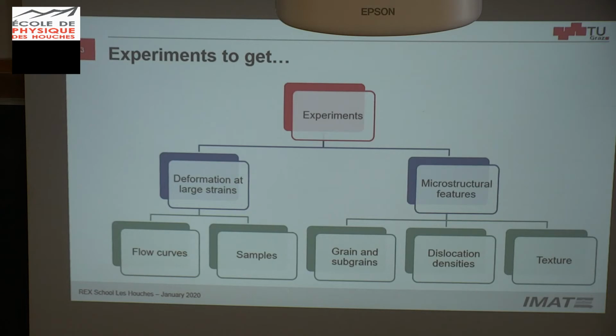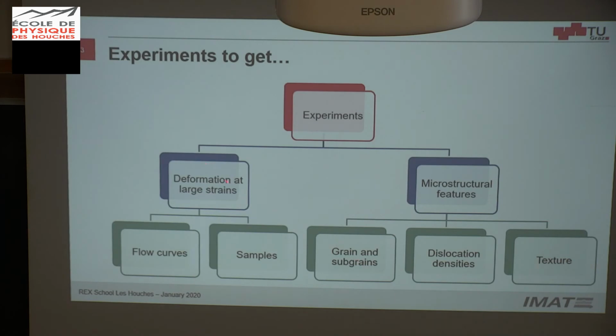So in the experiments, from deformation at large strains, we want to get the flow curves, of course, so stress-strain, and the samples for further investigation. You're laughing, but this is sometimes not understood. What did you do with the samples? I threw them away. I don't know the name. I changed. I mixed them. Okay, so the samples. You need the samples as well for microstructure investigation to obtain grains, subgrains, dislocation densities, texture, whatever information you want to get.